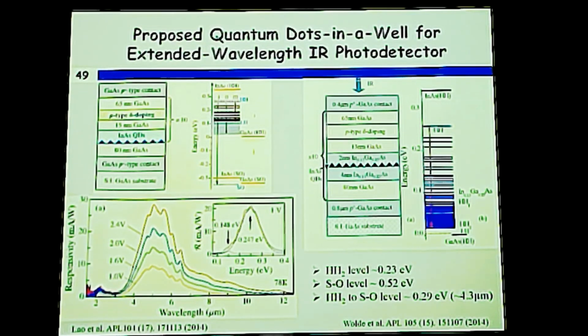Dot energy levels and well energy levels, whereas there are only dot energy levels here. Yes, the thing is, we are looking for a full width half maximum in the 3 to 5 range. For that, peaks should be close to 4 micron. That is one thing. Another thing is operating temperature. Now it is at liquid nitrogen temperature. The expectation with the new mechanism is that there will be a high barrier, so the operating temperature will also be much higher. That can be expected.